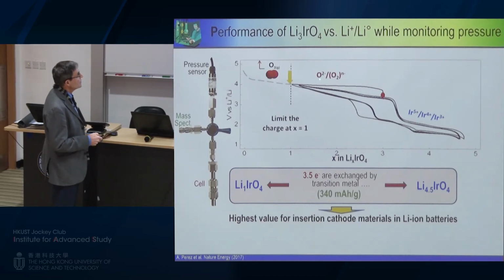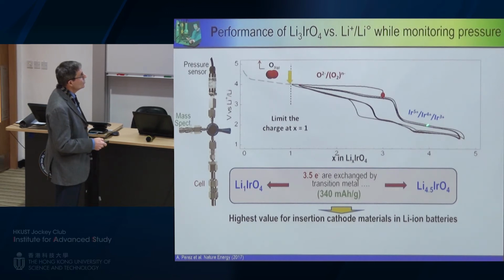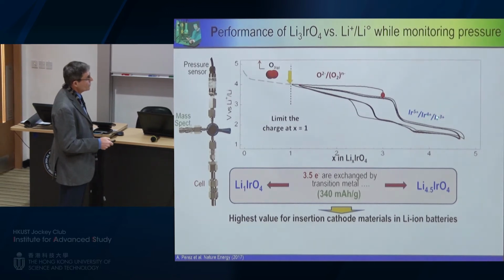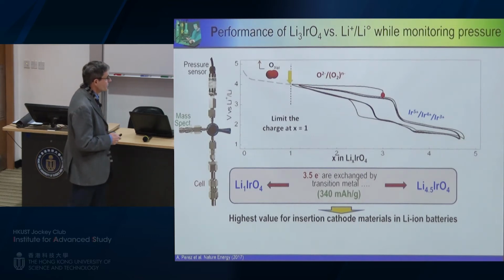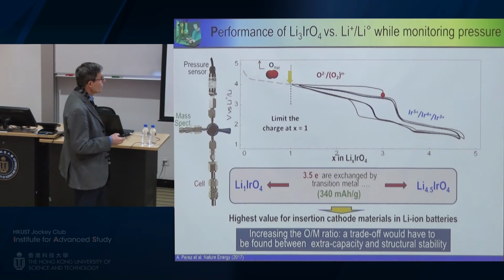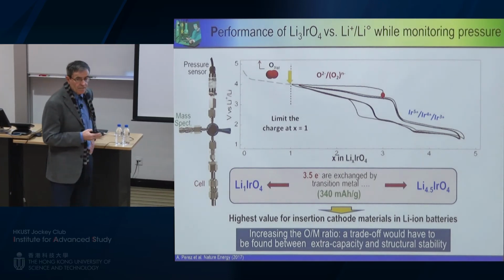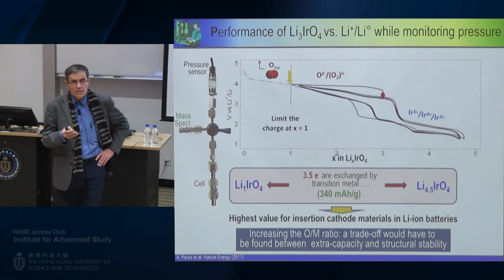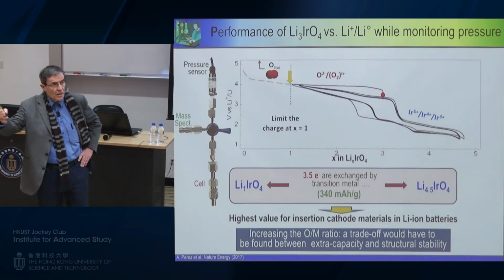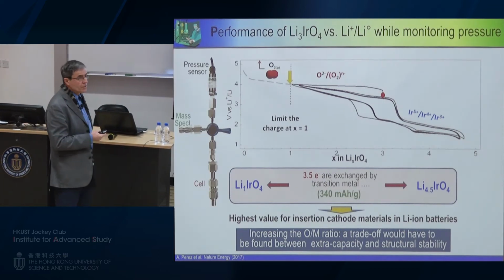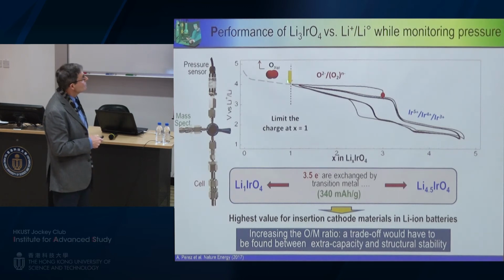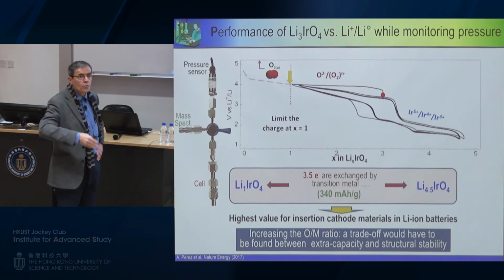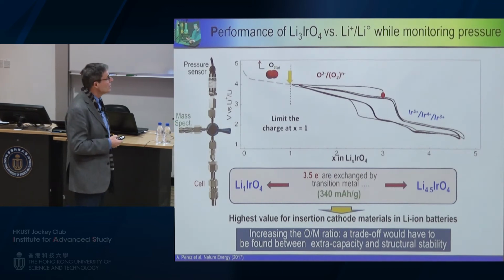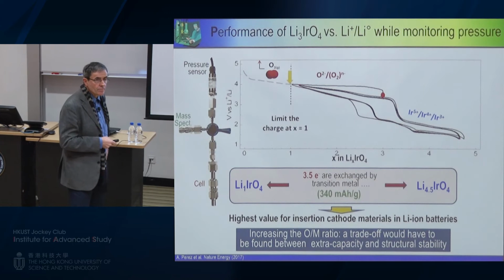And you can see this is really related to first the redox on the iridium, and here again the ionic redox activity. So this, of course, clearly indicates, as I mentioned to you, that there is a trade-off between extra capacity and, of course, removal of oxygen. And of course, the game in the field now is how can we get as much capacity without triggering this oxygen release, and this is the type of game that we are doing.